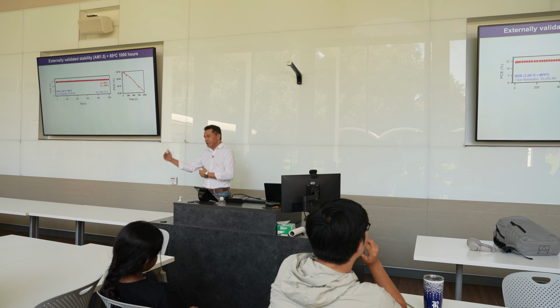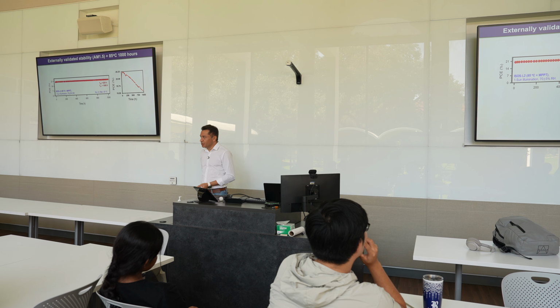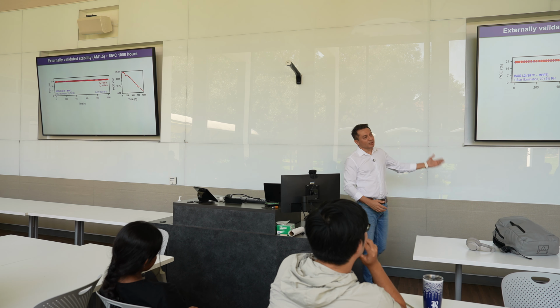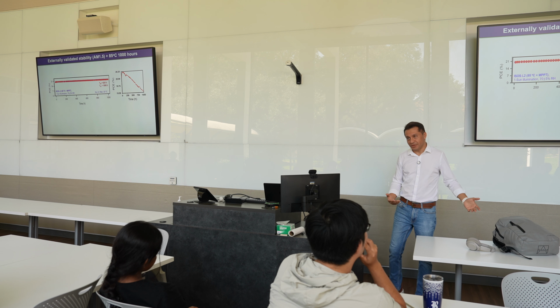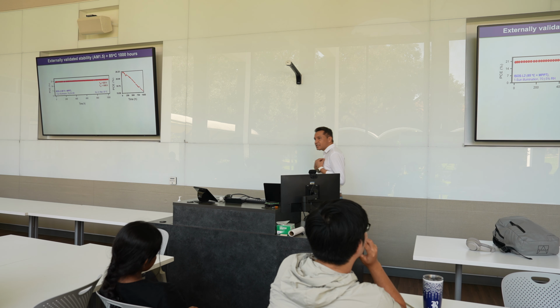Write a program so it keeps measuring your power conversion efficiency, and what you want to get is a straight line like that, a really flat line. You don't want it to drop, and that's really accelerated. And then you come up with an Arrhenius type model and figure out how long the solar cell lives. Well, it turns out if you do all of that, this solar cell would live on your roof for about 18 years, right? This is not us. This has been externally validated by 2 major PV giants, right? So we are very close.